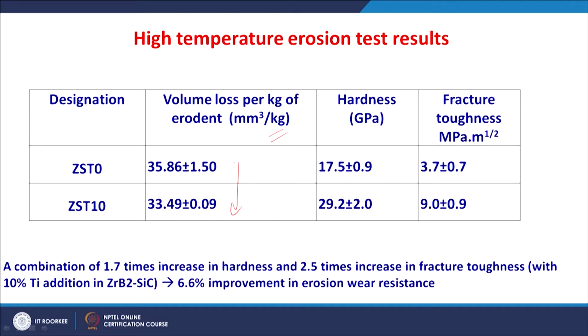And if you relate this erosion rate with the mechanical properties, we can see there is a large improvement in the hardness and fracture toughness, almost 1.7 times increase in the hardness and 2.5 times increase in the fracture toughness by adding 10% of titanium in the baseline zirconium diboride silicon carbide composite.